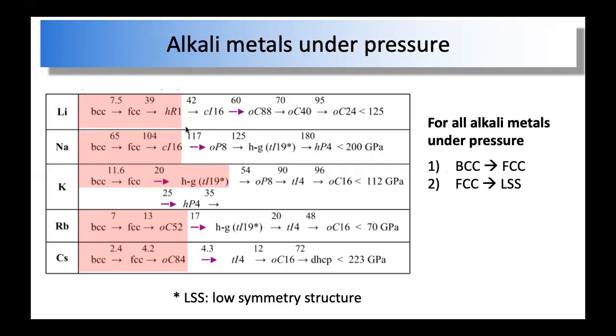And when we put pressure on it, we get more puzzles, right? For example, the alkali metals under ambient conditions are stable in the BCC structure. But when you apply pressure, most of them will transform into FCC structure. And if you keep increasing the pressure, all these simple structures become unstable, and then the system will start to adopt complicated structures with open sites and low symmetry. That is another very puzzling thing. We have some understanding of that, but not in a systematic way. So why do these very active, exemplar metal elements, under high enough pressure, abandon the close-packed structure, abandon the simple structure, and start to take complicated structures?